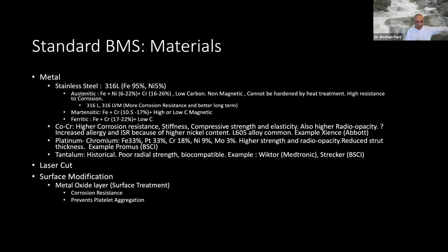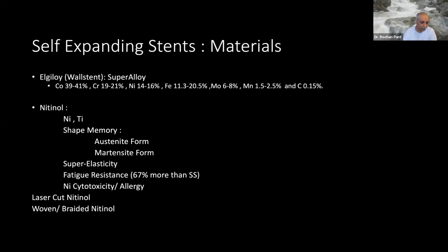Similarly, all these stents have a metal oxide layer on top by surface treatment that prevents corrosion and also supposedly prevents platelet aggregation because it's not a charged surface. This also undergoes more treatment to keep it smooth, to polish it to a high smoothness to reduce platelet aggregation and thereby thrombus formation. That is about the materials used for making stents and their treatment.